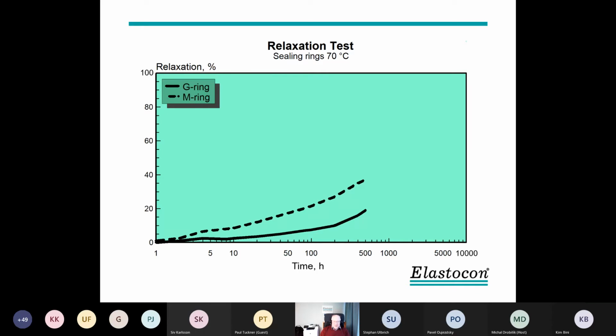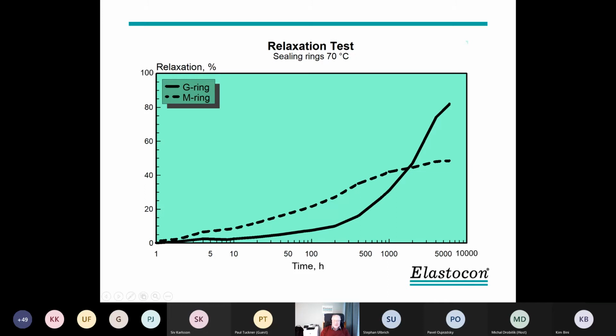And then there were people who wanted to do an extrapolation up to 100 years from these figures. There were a lot of discussions in the ISO committee about that. But we had results for 1 year, and then they look different. The one looking good to begin with, after 1 year, it's not much left of the sealing function. But the dotted line, we still have a sealing function which may work if the pressure of the seal is not too high. You can always speculate what is the difference.